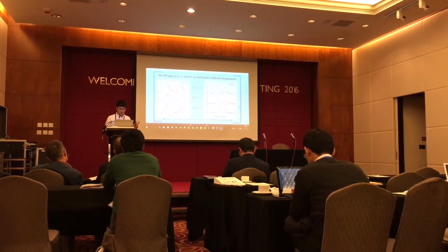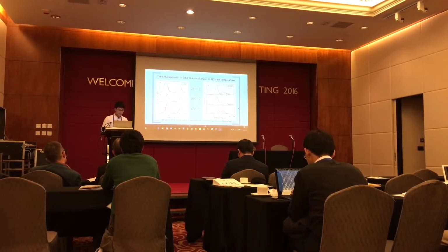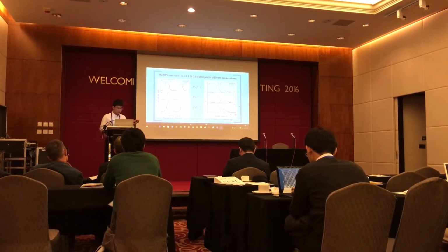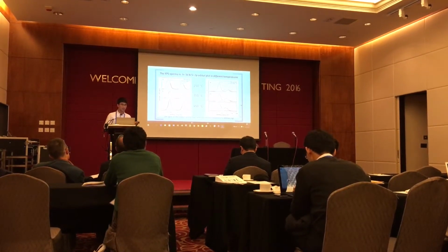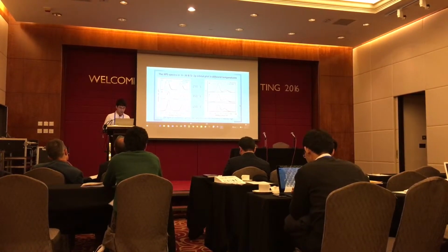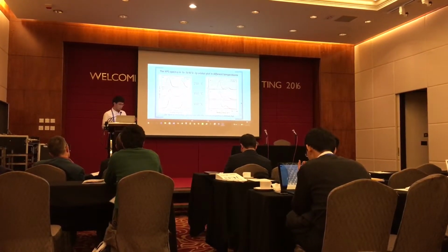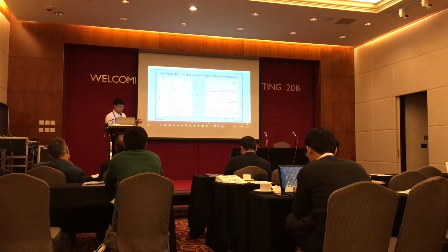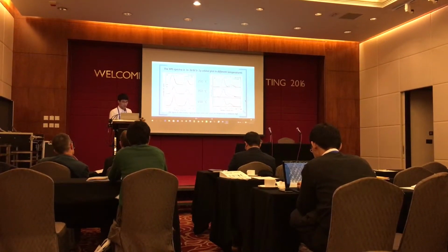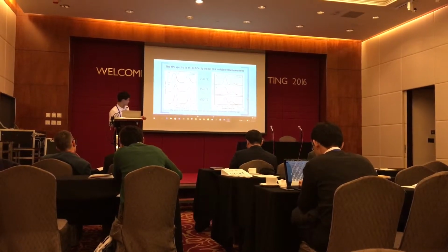There are two factors that can explain this phenomenon. First, due to lower density and larger particle size of nanodots at higher substrate temperature, the reaction area will become small, so the indium nitride signal will be weaker at higher substrate temperature.